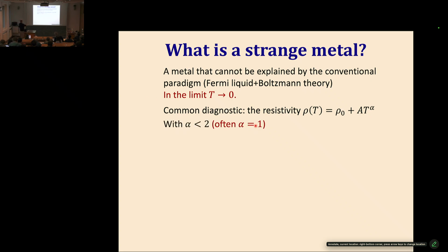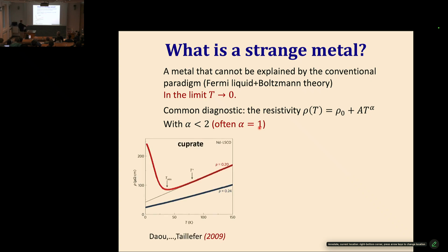Fermi liquid theory tells you that alpha should be 2. So the temperature dependence of the resistivity should be T squared. We'll go more into that in the next couple of slides. But anything which is less than 2 is a strong violation of the Fermi liquid theory. People often, in different systems, but not universally, find that alpha is equal to 1, namely the resistivity is linear in temperature. So here are some examples.